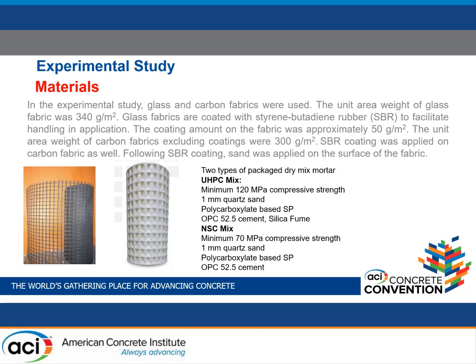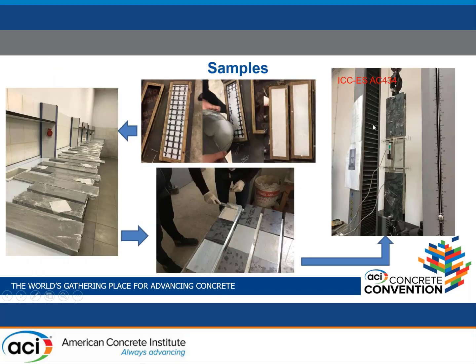Two types of packaged dry mix mortar were used in the experimental study. The first one was UHPC mix. UHPC mix had the minimum 120 megapascal compressive strength, maximum 1 millimeter dimension of quartz and polycarboxylate type superplasticizer, and ordinary Portland cement 52.5 and silica fume. And normal strength mix had 70 megapascal compressive strength, maximum 1 millimeter dimension quartz, polycarboxylate superplasticizer, and ordinary Portland cement. It does not have silica fume.